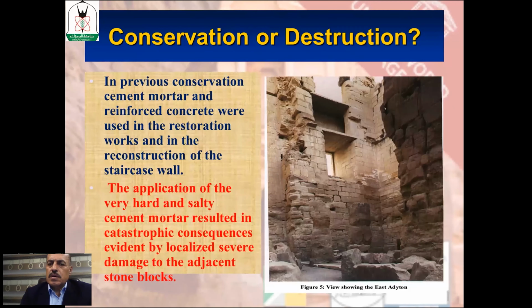In addition to deterioration and decay caused by natural factors, this monument suffered from bad conservation, what we call wrong conservation. In previous conservation trials, which happened 2 times, cement mortar and reinforced concrete were used in the restoration works and in the reconstruction of the staircase wall, as shown in this slide.